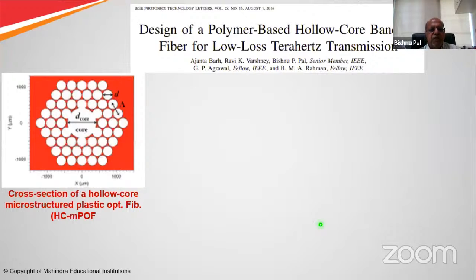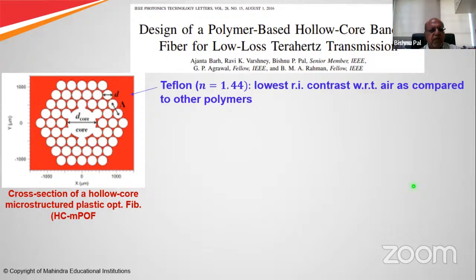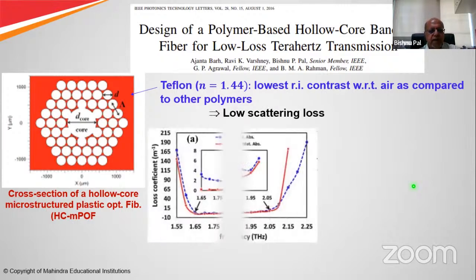And this is another fiber. We did it for terahertz transmission. In this case, rather than a photonic microstructure index guided fiber, it is a photonic bandgap guided fiber, with a larger central core surrounded by a photonic crystal cladding of air holes. The Teflon used in the red region has a refractive index of 1.44, which is the lowest refractive index contrast with respect to air compared to any other polymers. So it leads to low scattering loss, and this was published in Photonic Technology Letters.